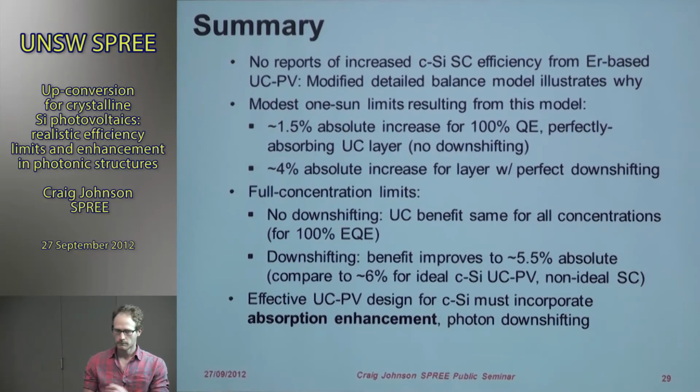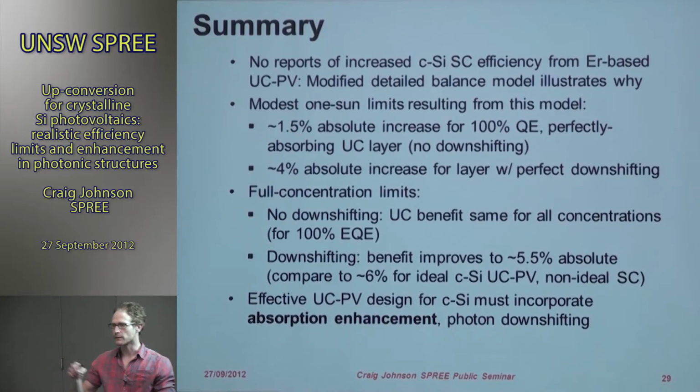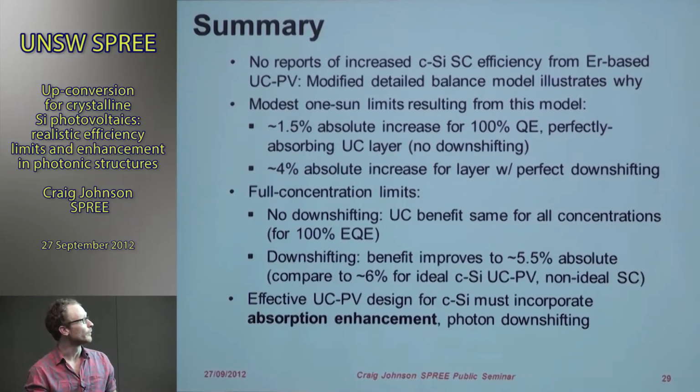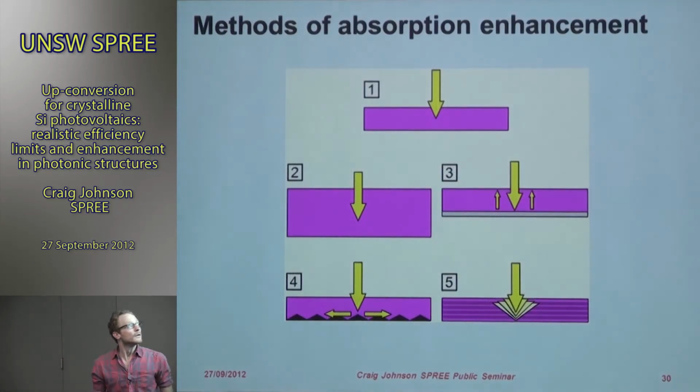And it does illustrate what we would need to do to an upconverter to really have effective designs for upconverting materials. One, they have to incorporate an enhancement of the intrinsic absorption. And two, downshifting appears to be key to designing an appropriate device. And just bear in mind that this all goes out the window when you consider realistic radiative properties.